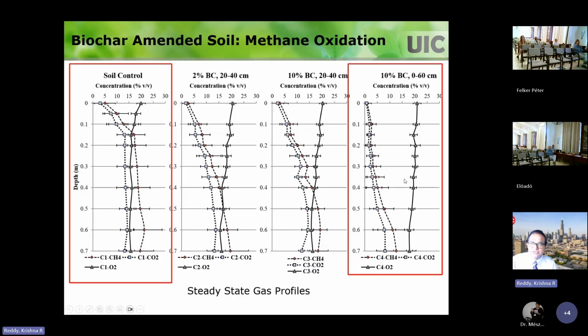But here, when you add 10% biochar to the soil, you can see significant reduction in the concentrations of methane and CO2. And also, the methanotrophs need oxygen. So we also monitor oxygen. You should not have any limitation on oxygen, because oxygen can enter from the top into the soil. So you're not really providing that oxygen, but that's why the cover systems are near the surface. So there's always ingression, and this can happen.